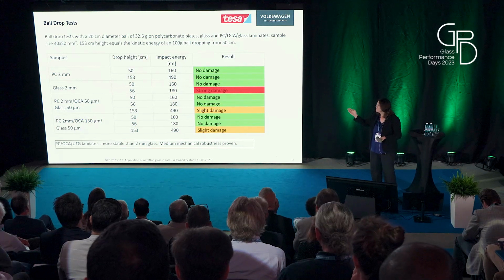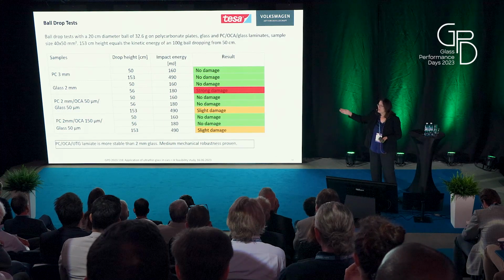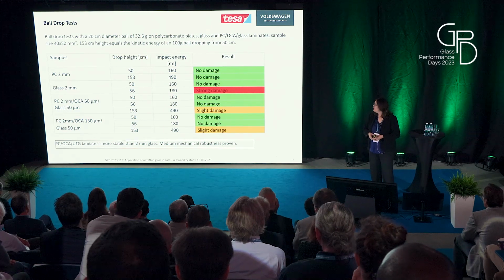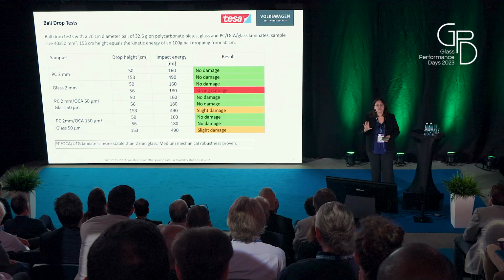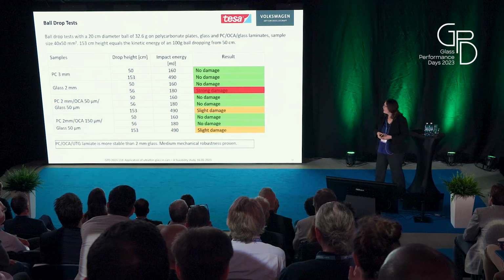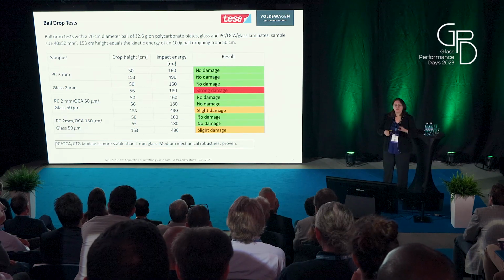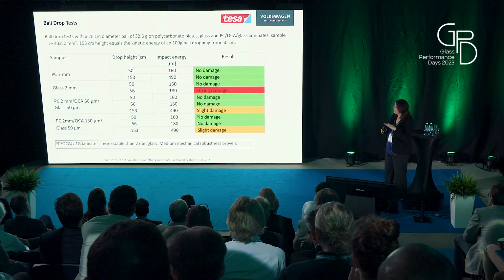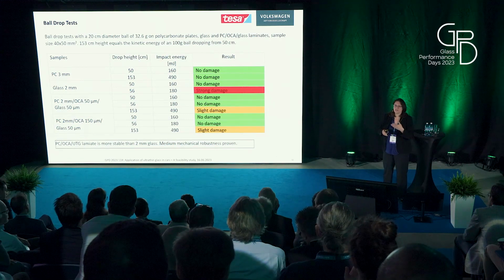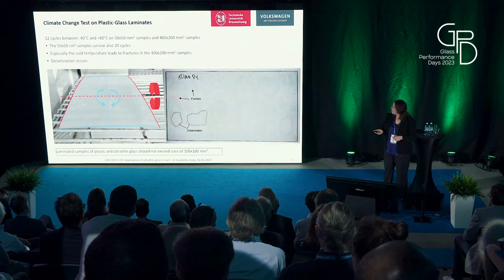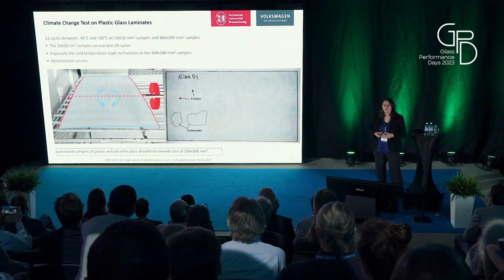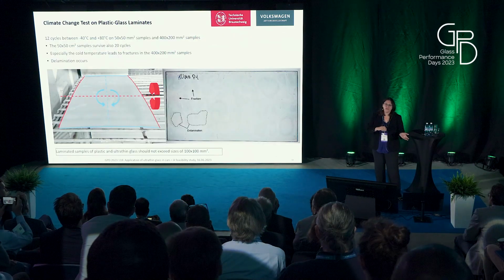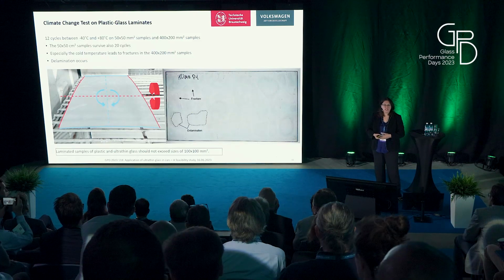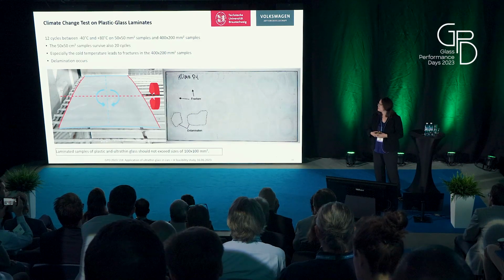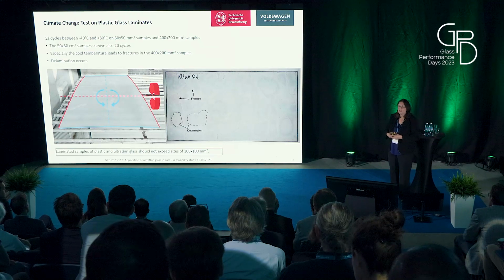But you see a slight damage at the maximum kinetic energy we chose here. But I think it's still kind of okay. We tested the limits here. Ball drop test, so moderate impact on such laminates will be no problem. What will be a problem is if you change temperature between -40 degrees and 80 degrees, and several times cycling these temperatures, which will occur in the field later on.